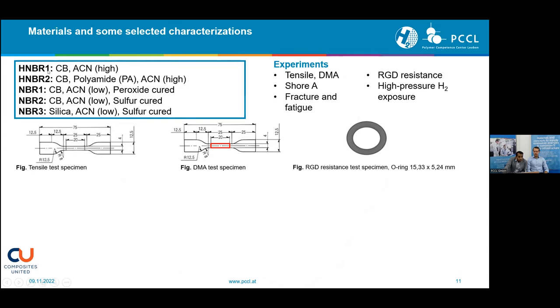First, a couple of HNBR grades. They are both CB filled, and one is additionally polyamide filled, and three NBR grades. So two are carbon black filled, and the third one is silica filled. And the first NBR one is peroxide cured. The other two are sulfur cured grades. So in this case, we see how these differences affect our properties.